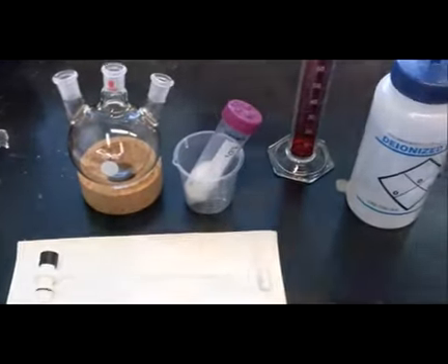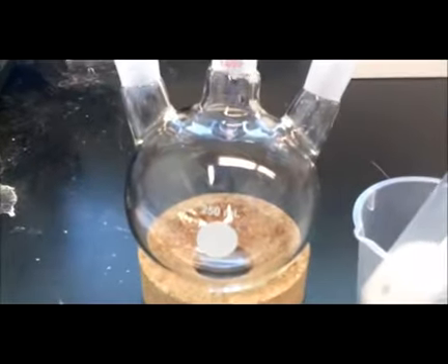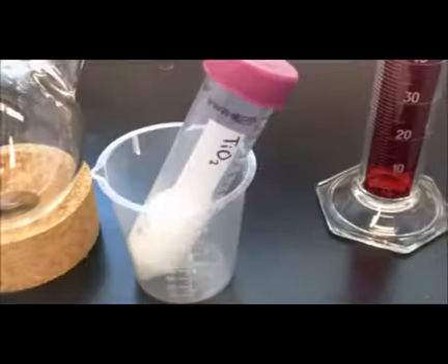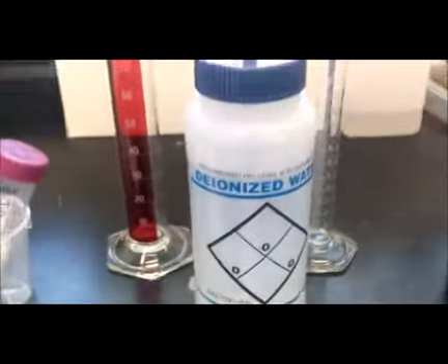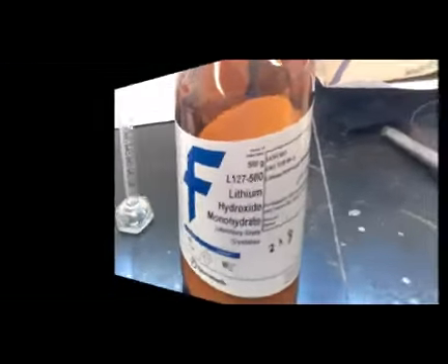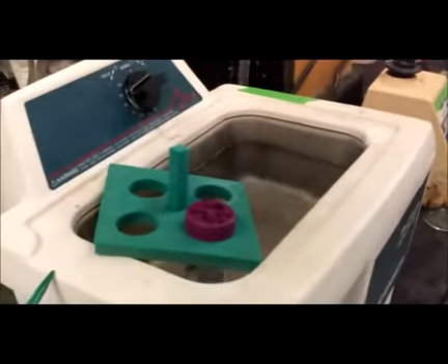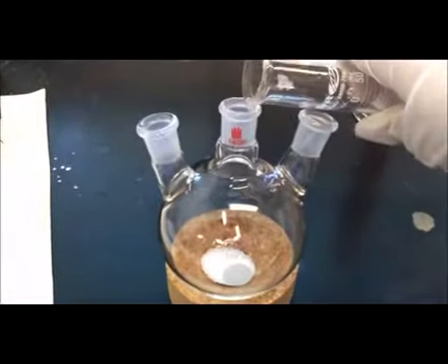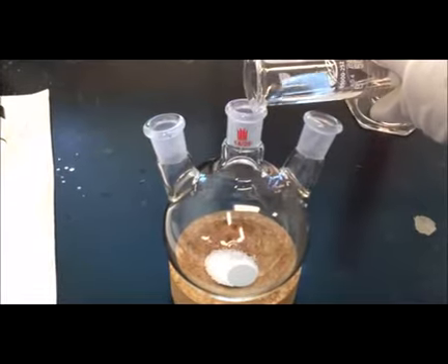In order to make the lithium titanate, we will need a 250 ml 3-neck round bottom flask, titania, deionized water, and lithium hydroxide. We first have to sonicate the titania and disperse it completely in some of the 150 ml of water measured out. While the titania is sonicating, we weigh out 1.5 grams of lithium hydroxide. We add some water and swirl to dissolve.